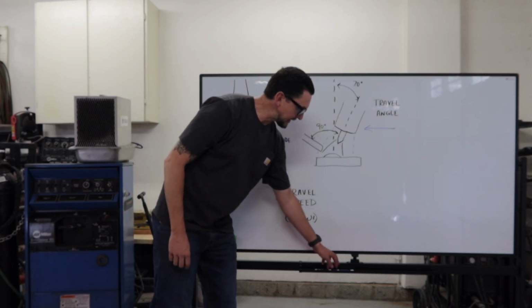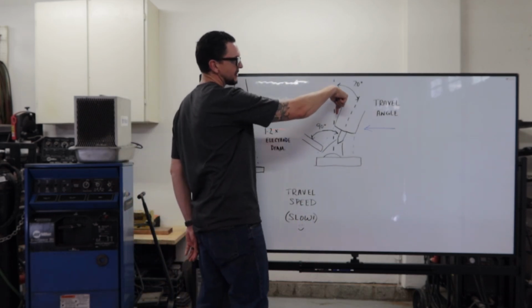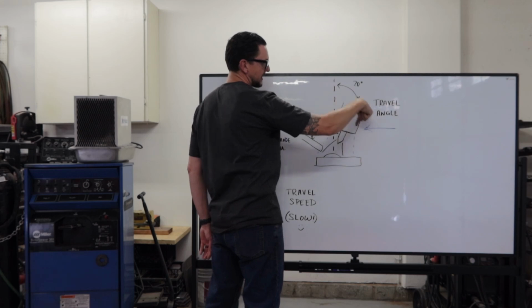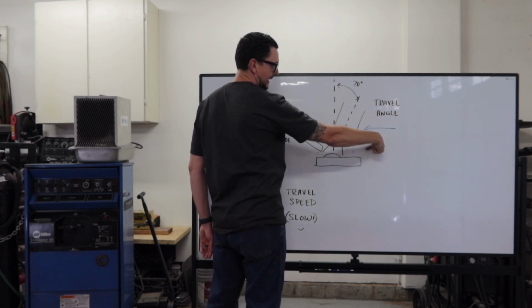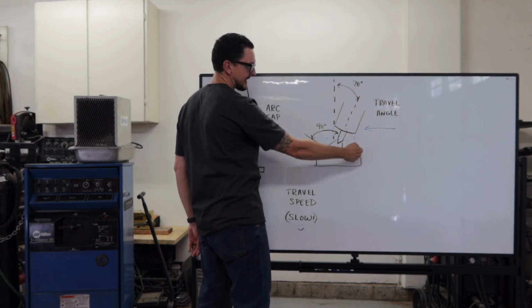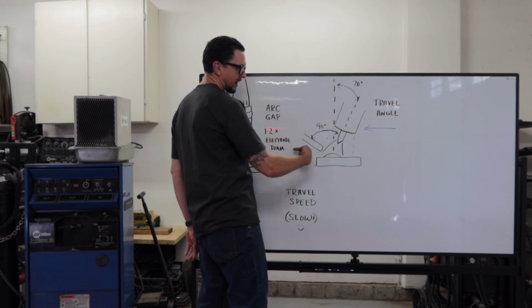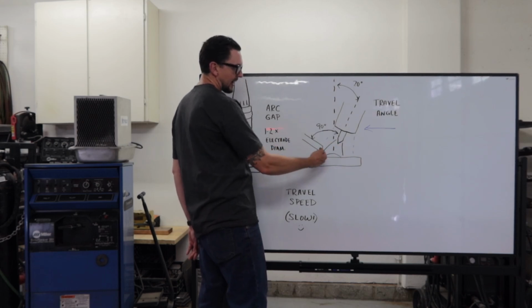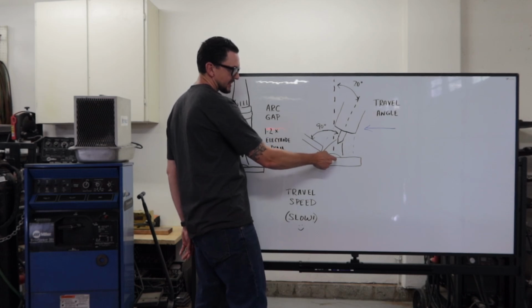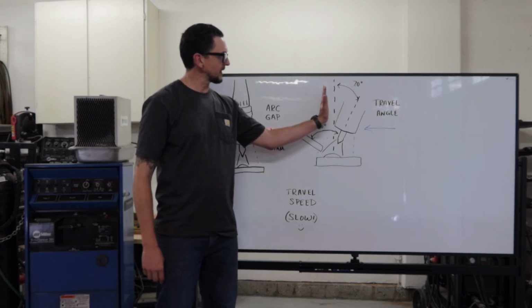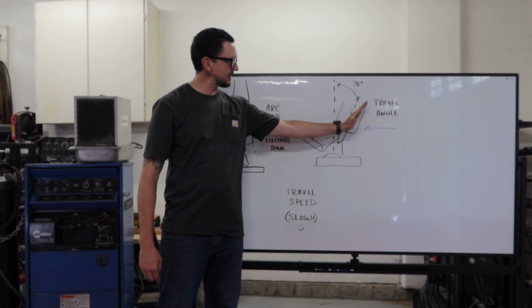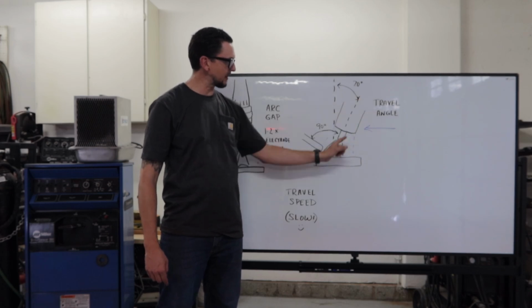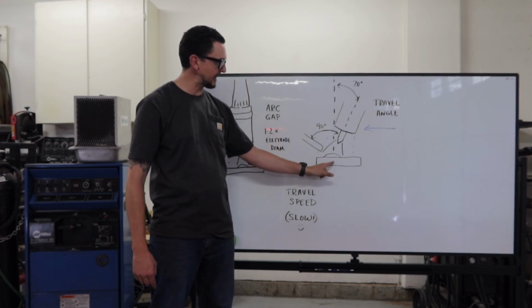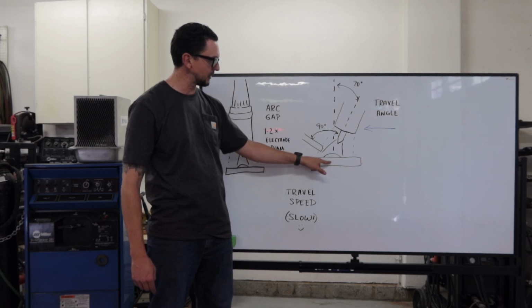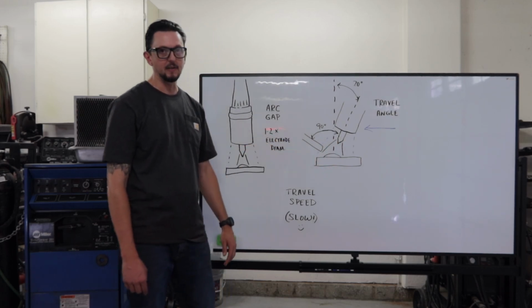So in terms of travel angle, we want to make sure that our angles aren't too extreme. We don't want to use too much of a push travel angle, because then that just directs our arc and our heat out the front rather than into the base material. So we want to make sure it's about a 20 degree off of 90 push angle, so that we're directing the heat down into the base material, into the weld pool, and not towards our filler metal.